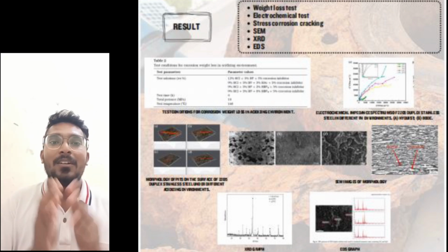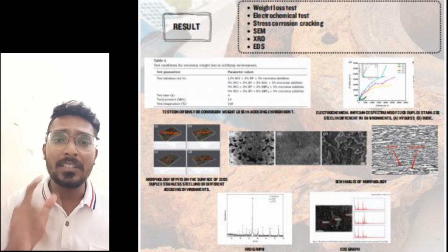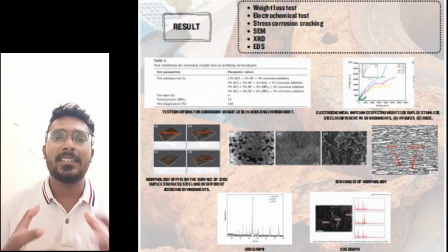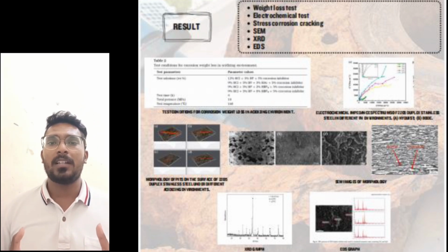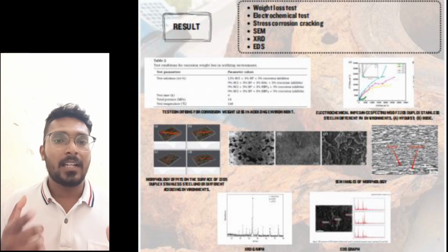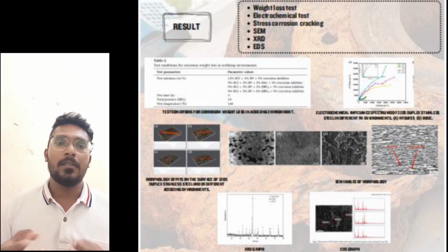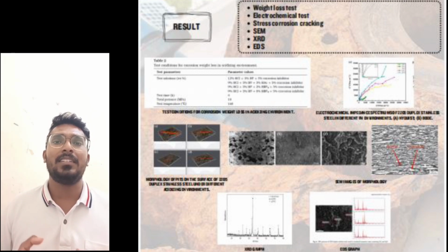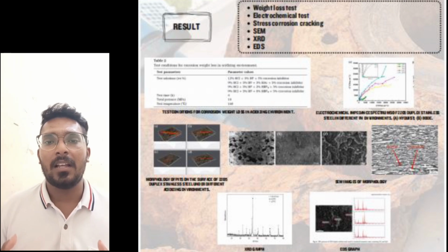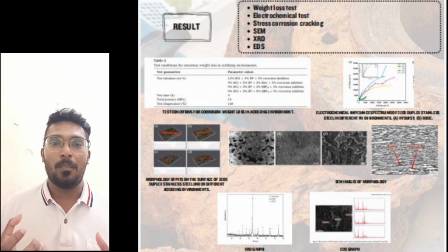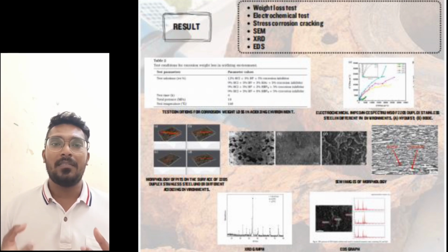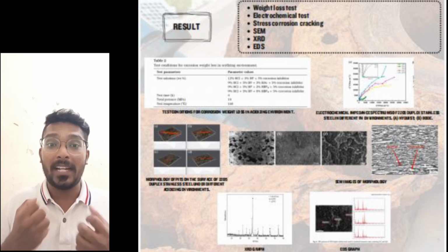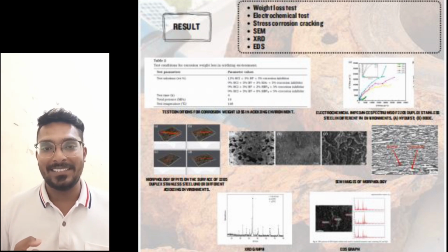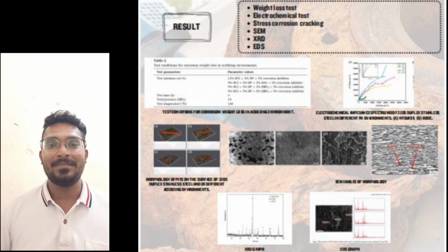The XRD analysis was conducted to identify the corrosion products on the surface of the coupon samples in the production environment. The results show that the main corrosion products were iron sulfate and iron carbonate. So these are the XRD results that we obtained. And finally, the EDS analysis identified iron sulfate and iron carbonate as the main corrosion products in the production environment, where hydrogen sulfide and carbon dioxide contribute to the formation of the protective layer and change the stainless steel corrosion resistance. So let's move to the next part.